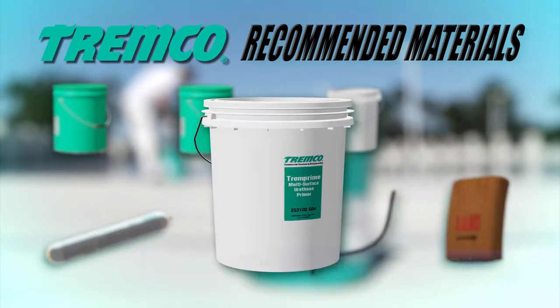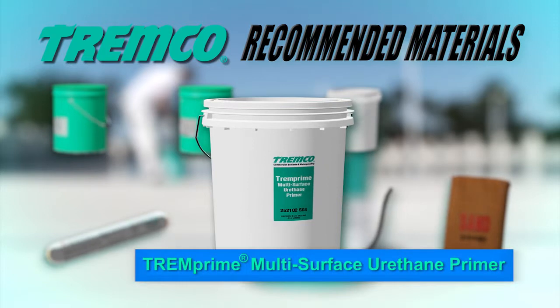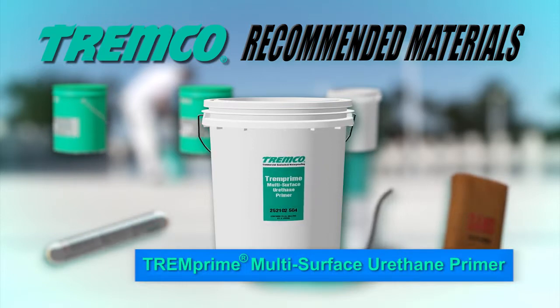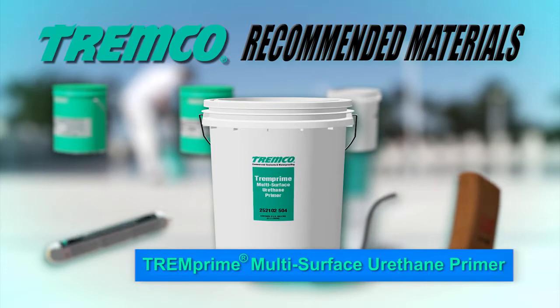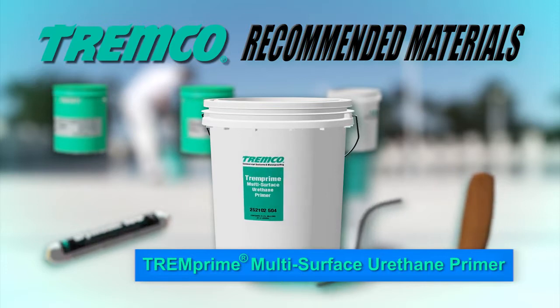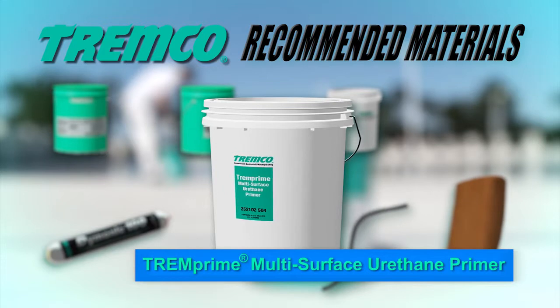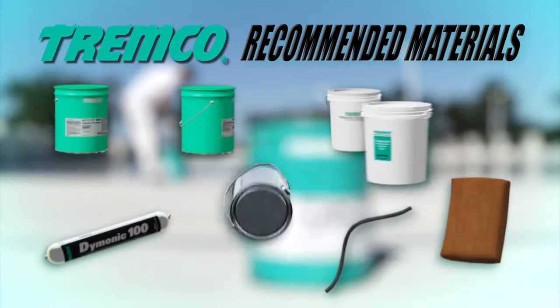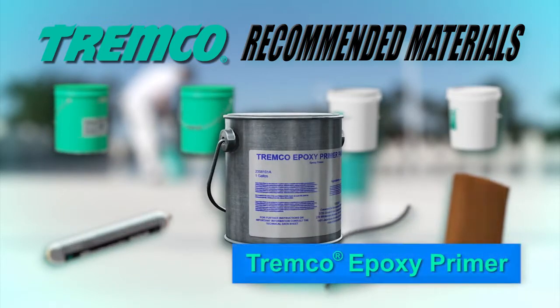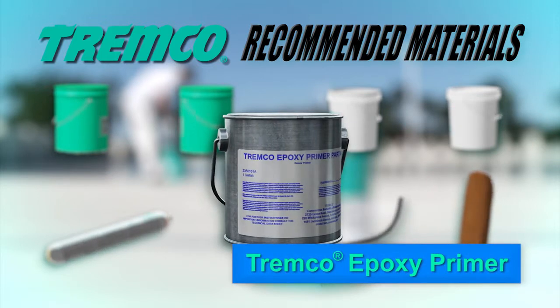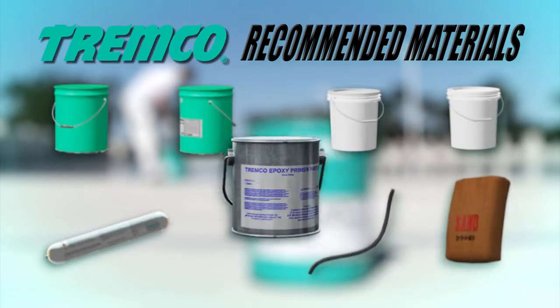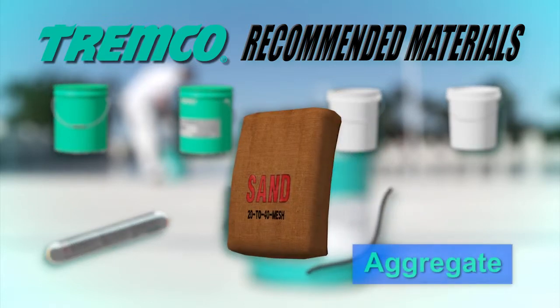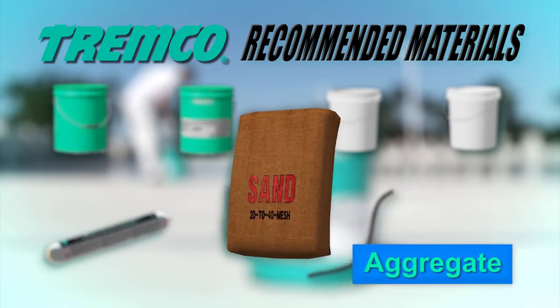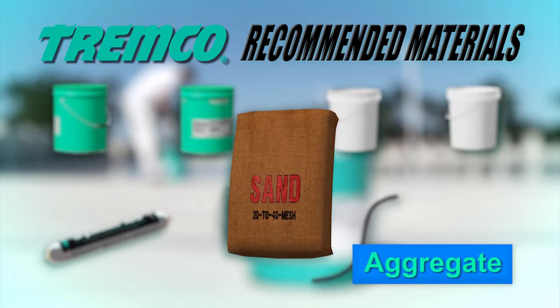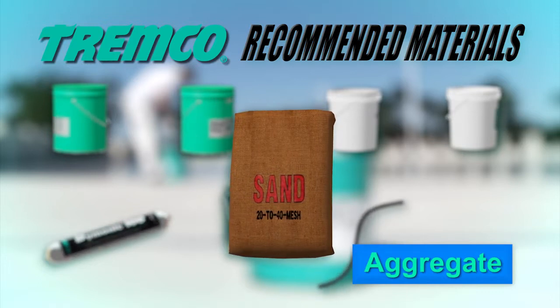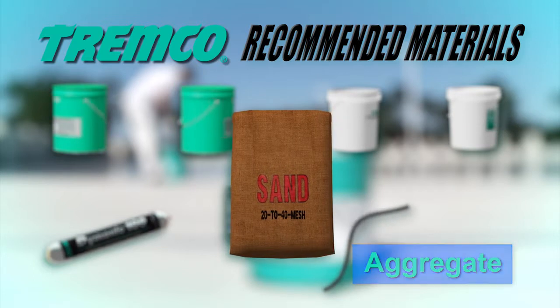TREMprime Multi-Surface Urethane Primer is a VOC-compliant, quick-drying, two-part primer, excellent for use between two layers of urethane deck coating and can be used as a primer on all common construction substrates, including wood, concrete, PVC, and steel. Tremco Epoxy Primer is a two-part epoxy primer that's used with sand to level surfaces before applying the base coat. The recommended aggregate for use with this deck coating system is a 20 to 40 mesh or 0.6 to 0.9 mm diameter silica sand or aluminum oxide, which imparts a textured finish and contributes to wear resistance.